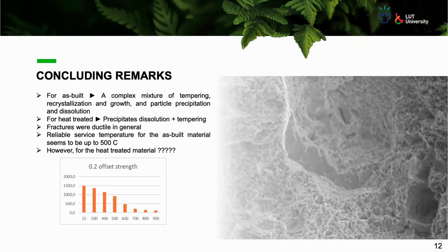But based on what we have here and our results so far, we can say that at high temperature for the as-built specimens, a complex mixture of tempering, recrystallization, and grain growth, and of course, particle precipitation and dissolution contribute to the material behavior, while for the heat-treated version, the mechanism is simpler. The precipitation, dissolution, and tempering are the main factors. Fractures practically were ductile regardless of the material condition.